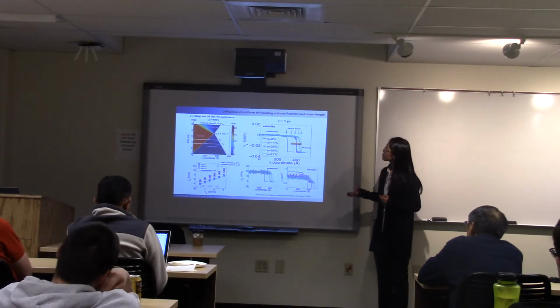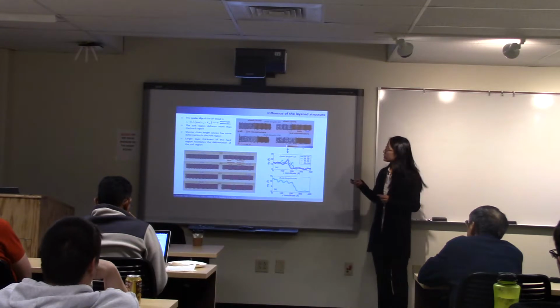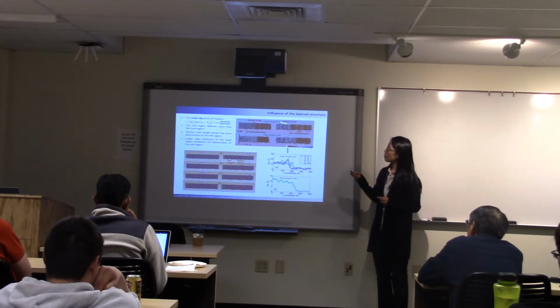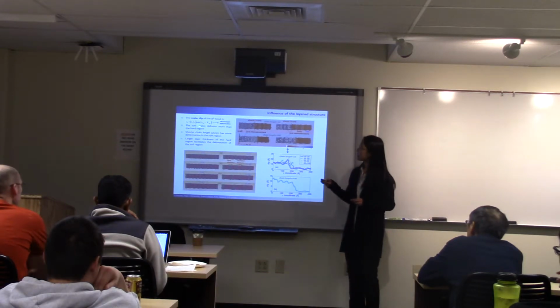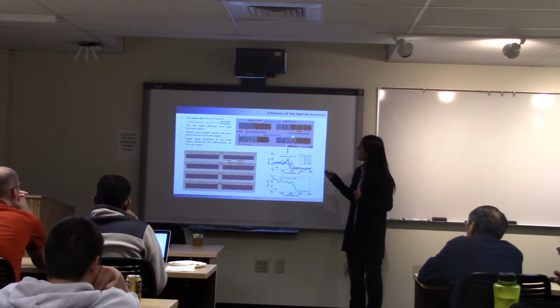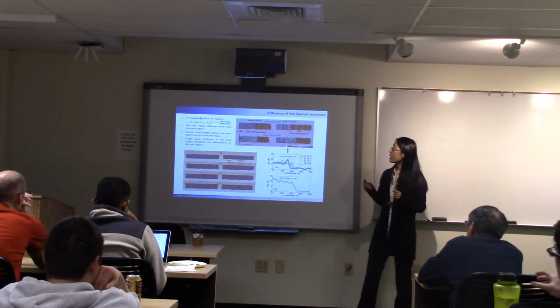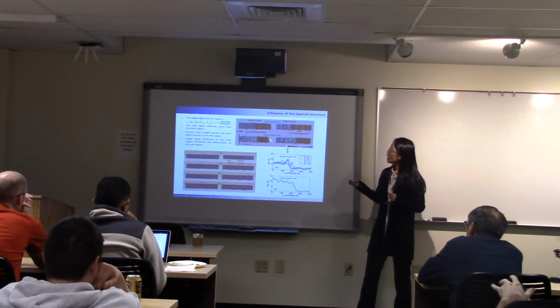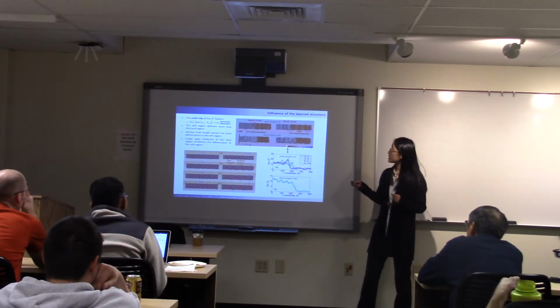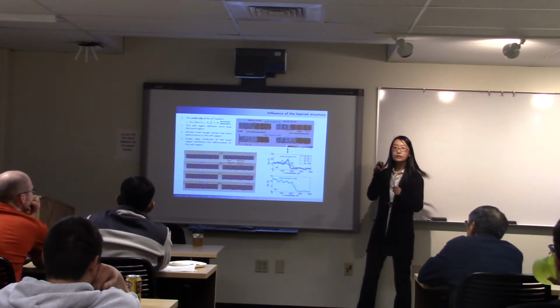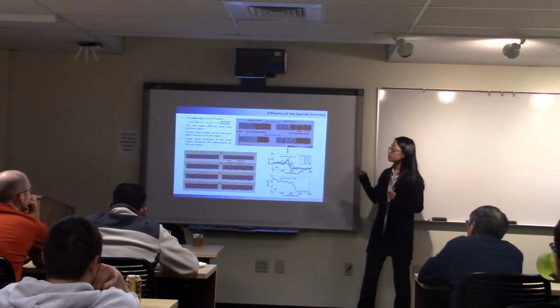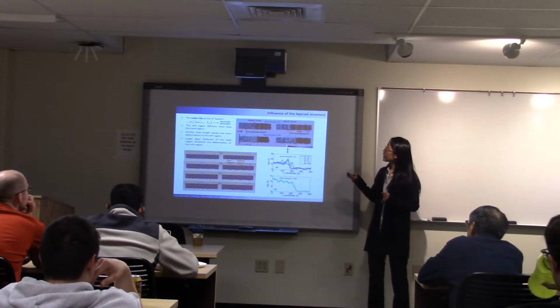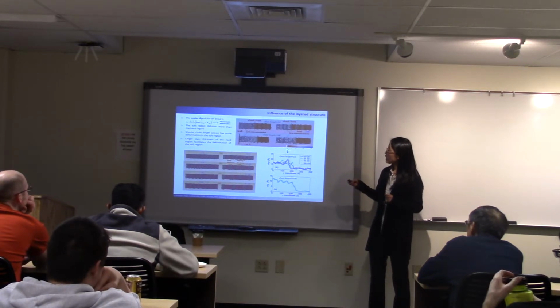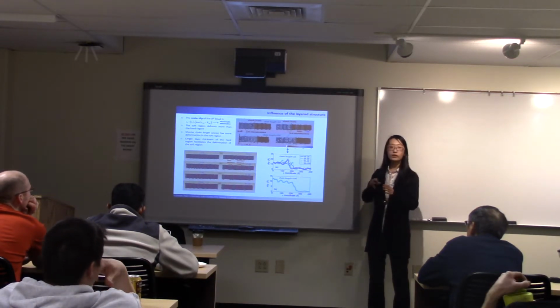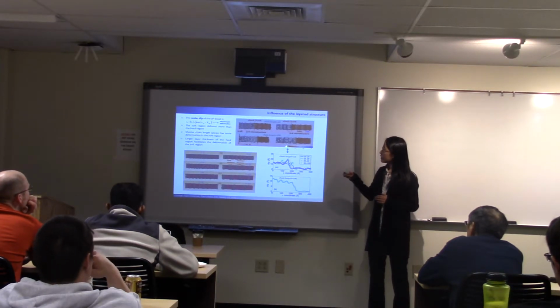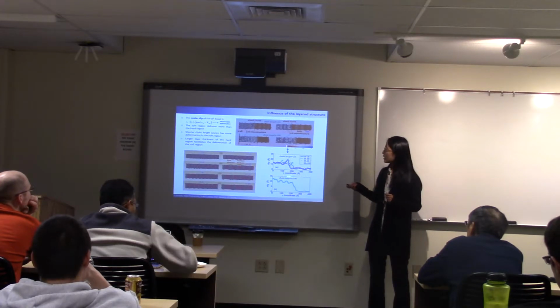also the chain length. So besides the uniform nanoparticle loading, we are also interested in the influence of layer structure. So we computed the scalar slip of all the superatoms and plotted it here, which is an indication of the microscopic deformation. We can see the shock front very easily by the contrast in color, where the red color is very close to 0 scalar slip, and the blue color is very close to the maximum scalar slip. We also compare two different chain length systems, combined with this figure, which is an average over the YZ plane of this figure and shows a variation of the scalar slip along the x direction.